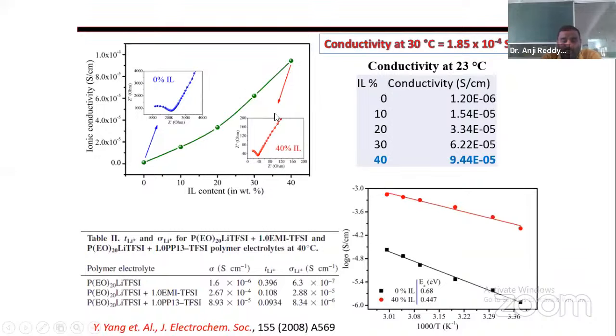Here I have compared this work with another work with LiTFSI. Same polymer, whatever I use, the same polymer. In this work, whatever polymer and ionic liquid they use, I use the same, but I changed the lithium salt. In this work they use LiTFSI, I use LiDFOB. We have achieved very good conductivity compared with this one. At 40 degrees centigrade, they reach the highest conductivity of 2.88 x 10^-5. At 30 degrees centigrade itself, we have achieved 1.85 x 10^-4 when using LiDFOB. This is one of the very good stable lithium salts, LiDFOB.